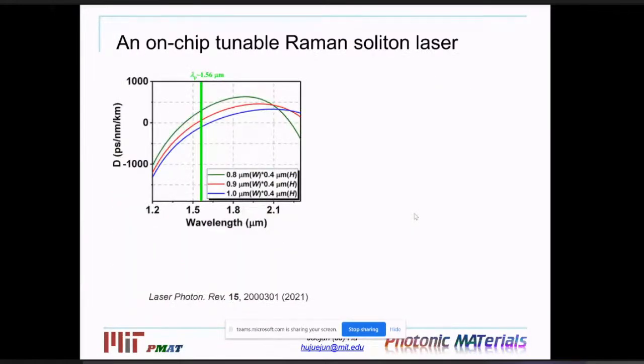Now, specific to the design of the waveguides, we have to be very careful about engineering the dispersion characteristics of the waveguide. It turns out that for all these nonlinear processes, the dispersion of the waveguide dictates the phase matching condition in the nonlinear interaction, and therefore it also dictates the regime of interaction at which our device will operate. What I'm showing you here is a plot of the group velocity dispersion as a function of wavelength, plotted for three different waveguides with widths from 0.8 microns to 1 micron.